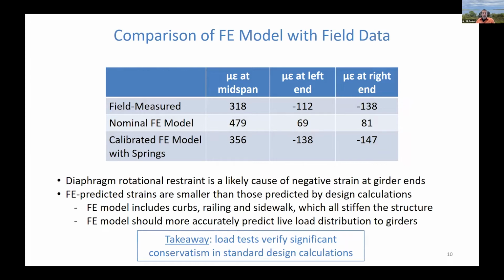And I should point out that the nominal finite element model with no springs on the end predicts higher strains, of course, than one with the springs on the end. And those strains, however, are smaller than those we get from our design calculations because that FE model, of course, includes curbs, railings, sidewalks, all these other elements which tend to stiffen the structure. That FE model will also more accurately predict our live load distribution to the girders.